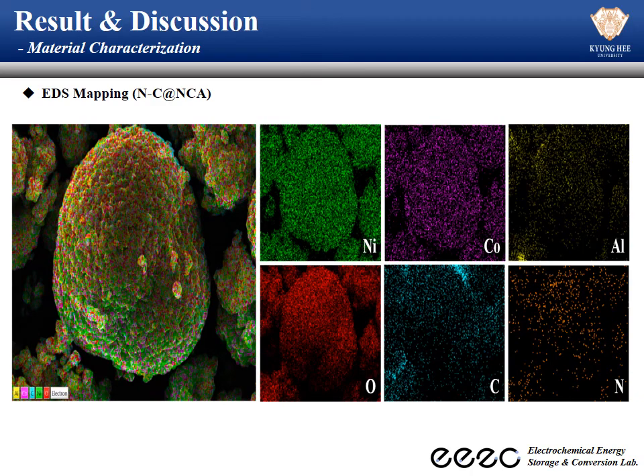In addition, as a result of confirming the elemental composition of N-C@NCA through EDS mapping, it can be confirmed that the nitrogen-doped carbon coating layer was formed on the NCA through the fact that carbon and nitrogen appeared in addition to nickel, cobalt, aluminum, and oxide of NCA.